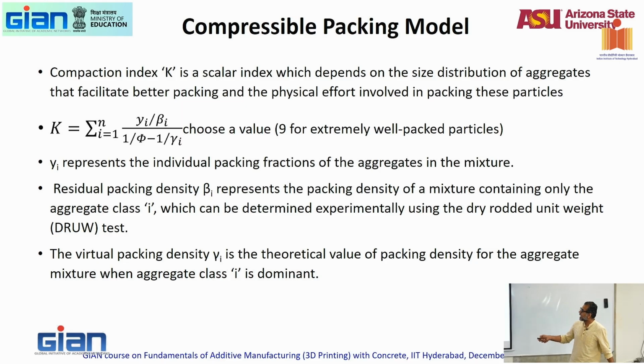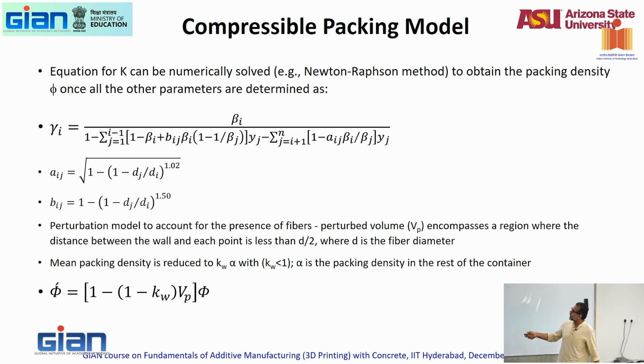Good. Beta i is a residual packing density, which is the packing density of a mixture consisting of only the aggregate class i, which is your dry rodded unit weight. You can use a dry rodded unit weight for that class of aggregates. And virtual packing density, gamma i, is a theoretical packing density when class i is dominant. There are ways in which you can do a theoretical packing density. You can either do it computationally or through a series of experiments and minimize the results of all the experiments. So this involves quite a few experiments. And then you can solve this. So this is gamma i, which is beta i over this big function where a_ij and b_ij are the loosening effect, wall effect, and the effect of fibers and all of that. Based on the aggregate sizes, you can get the loosening effect and the wall effect. So that gives you gamma i.